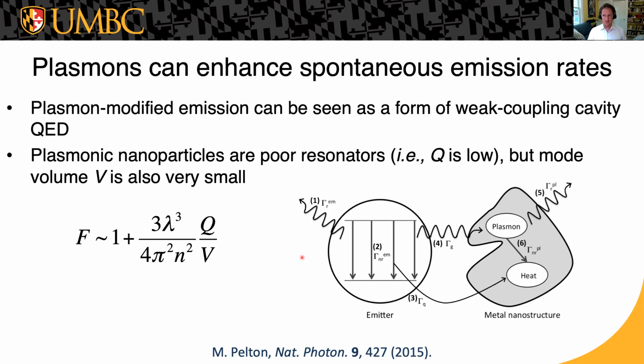But now the cavity is this plasmonic resonator, which can confine fields to subdiffraction-limited volumes. So in the language of cavity QED, the enhancement that you got for the spontaneous emission rate, the rate of emission into these cavity modes compared to the free space emission rate, was proportional to the quality factor of the cavity, the photon lifetime, and inversely proportional to the mode volume, how tightly confined the light is. Ordinary photonic cavities are limited by the diffraction limit to have a mode volume of about half a wavelength on the side. So if we carry this idea over to these plasmonic cavities, and keeping in mind that